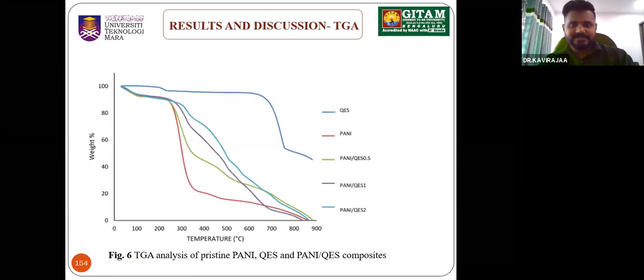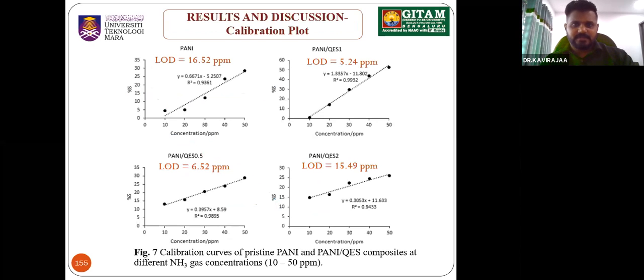Next slide. Okay, for the thermal stabilities, obviously QES performed with the highest thermal stability because of the inorganic substituent. But interestingly, compared to the pristine PANI, the composite materials exhibited slightly higher thermal stability. So it shows that they have a certain degree of higher thermal stability compared to the pristine PANI in the study. Okay, next slide. So, about sensor measurement.